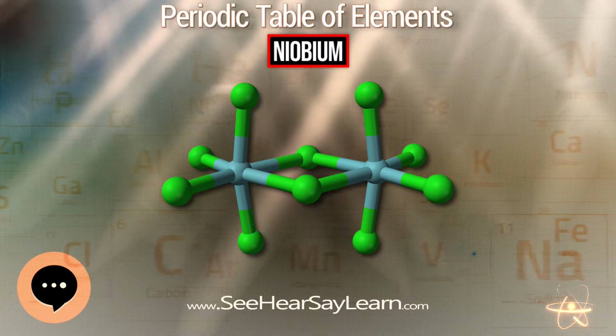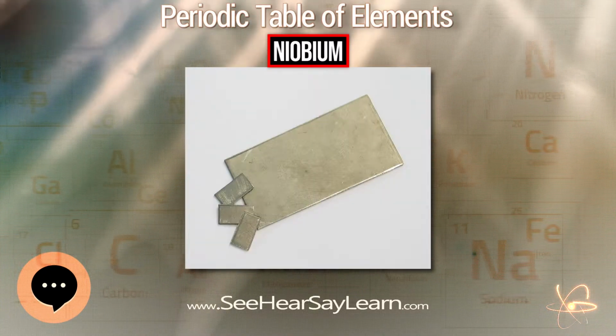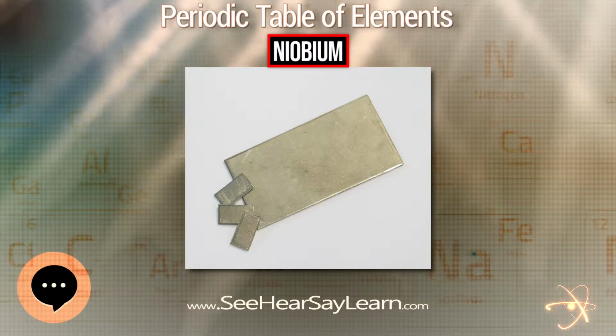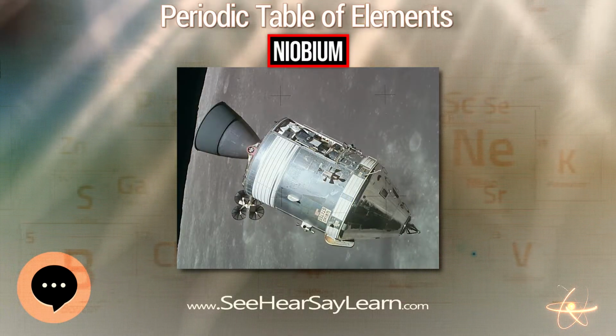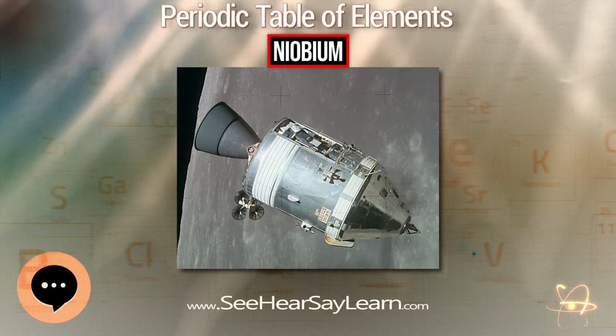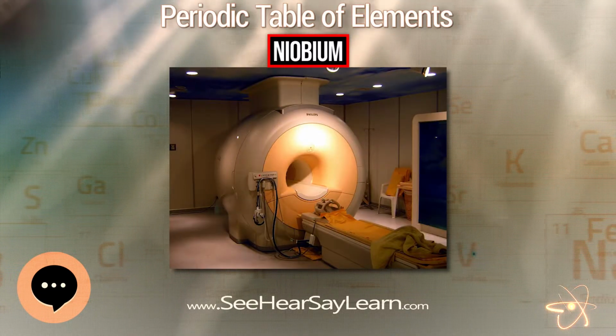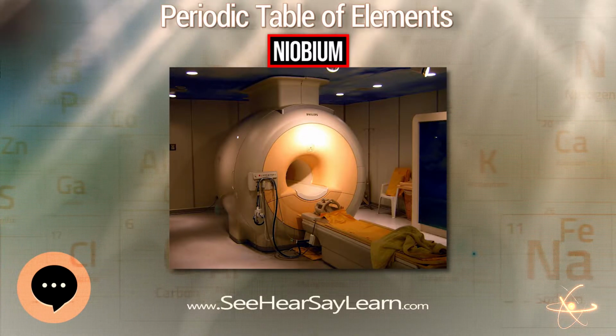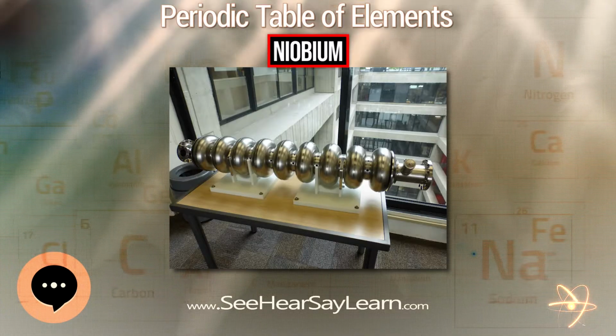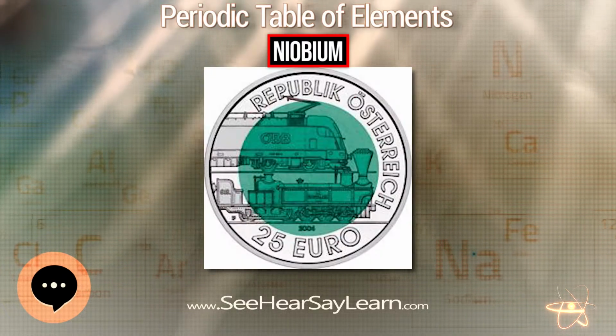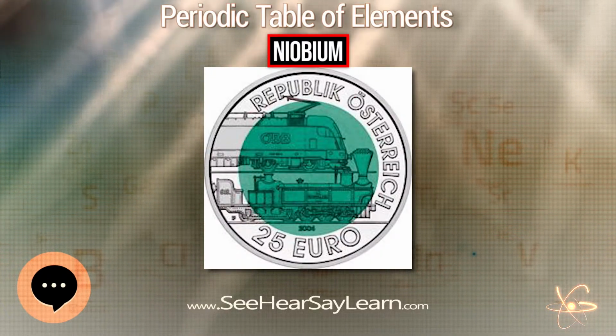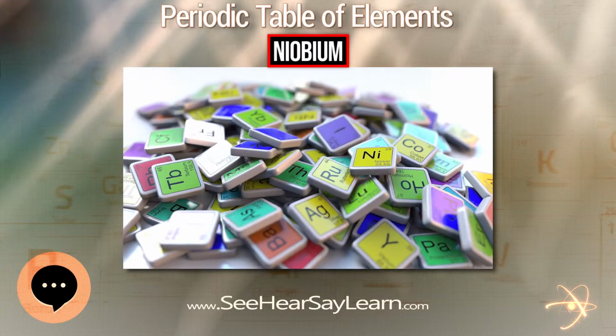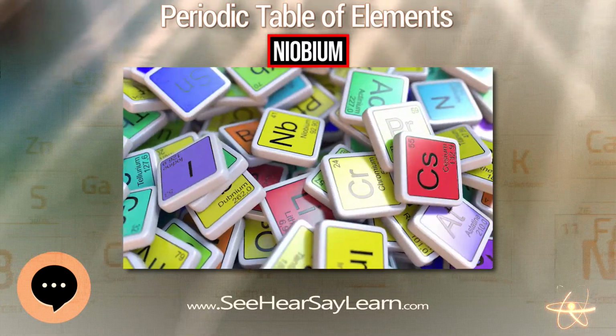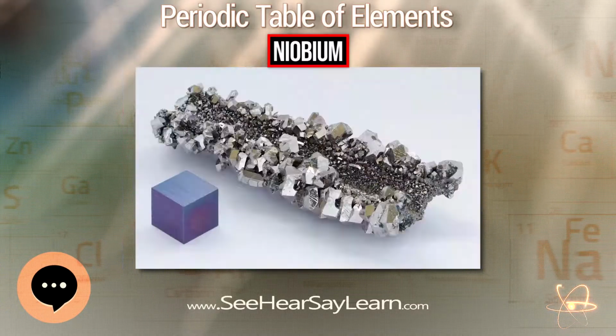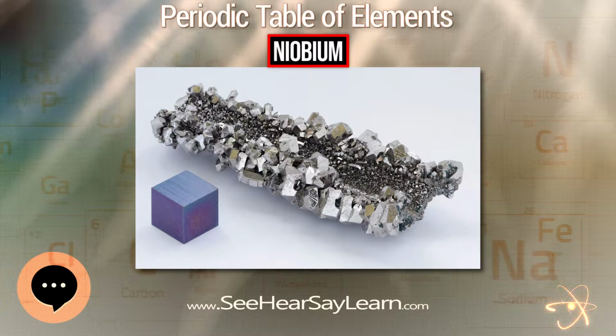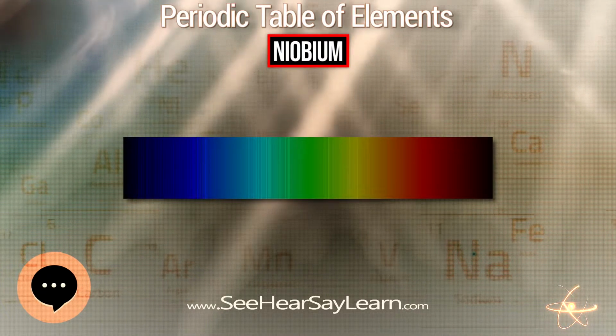In many ways, niobium is similar to tantalum and zirconium. It reacts with most nonmetals at high temperatures, with fluorine at room temperature, with chlorine and hydrogen at 200 degrees C, and with nitrogen at 400 degrees C, with products that are frequently interstitial and non-stoichiometric. The metal begins to oxidize in air at 200 degrees C. It resists corrosion by fused alkalis and by acids, including aqua regia, hydrochloric, sulfuric, nitric and phosphoric acids. Niobium is attacked by hydrofluoric acid and hydrofluoric/nitric acid mixtures.